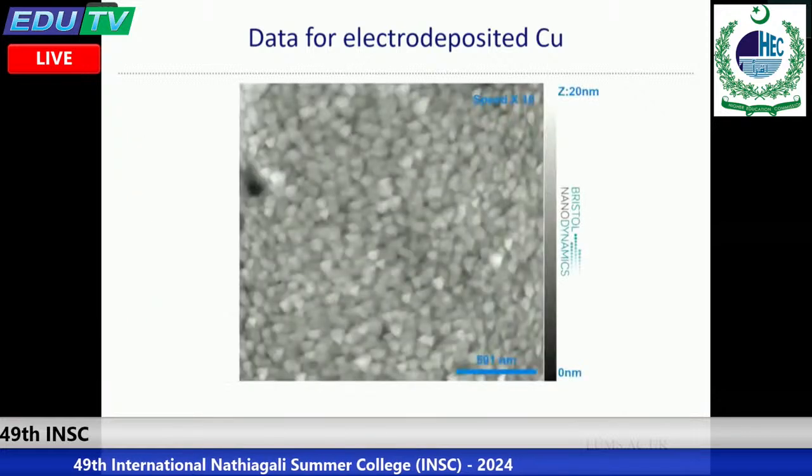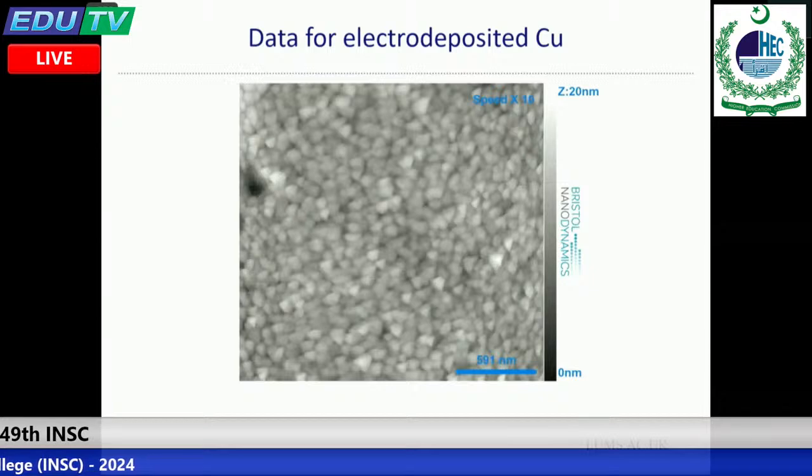What I'll do now is show you a video of the surface actually growing. You can tell that this data is not perfect because you can see that a particular triangular shape is appearing. That triangular shape is something you should always watch for if you do atomic force microscopy, because it tells you that you are partly imaging your tip. So this data has a convolution of features from the tip and features from the actual surface. But the surface coarsening phenomenon that you see is real.